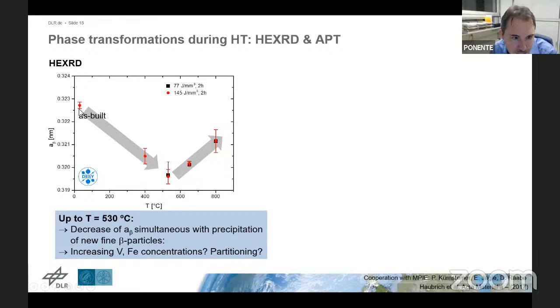At 400 and in the as-built state, we had these fine, thin white films between the martensite lath. And here we have this coarsening particle type microstructure. So this kind of resembles itself in the lattice parameter. And that's already telling us something about the composition of the beta phase here. This lattice constant typically goes down if the amount of beta stabilizers, so vanadium and iron in this alloy, increase in the beta phase. This kind of shrinks the lattice constant. So this is already a strong hint that there is a partitioning effect and diffusion going on in the material.